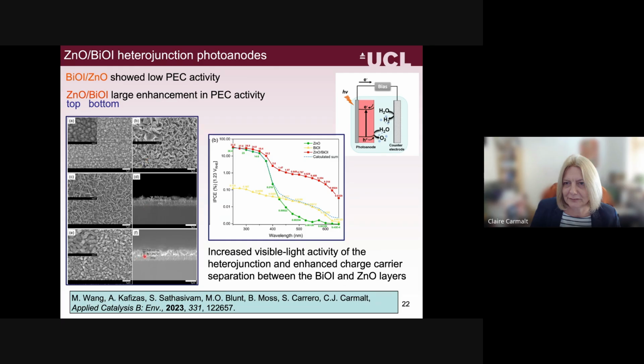And then the other way around, when you have the bismuth oxyiodide on the bottom and zinc oxide on the top, you can see it adopts a very similar morphology to the zinc oxide. Now, if the bismuth oxyiodide is on the top, that doesn't work very well.